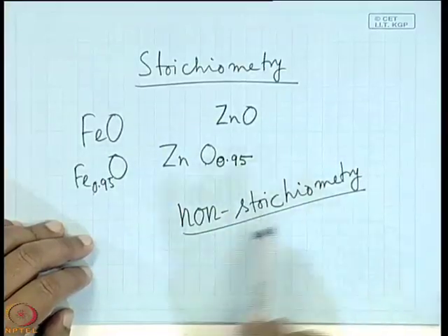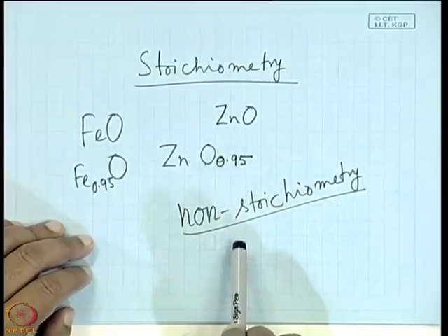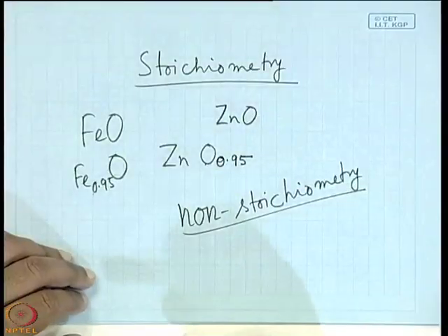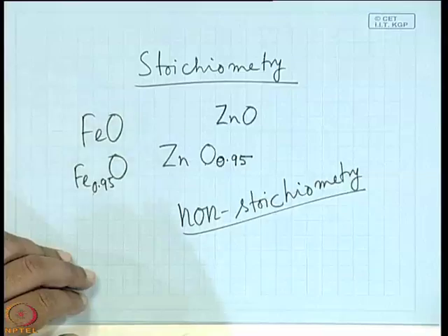That is the reason, because of this non-stoichiometry. In nature these materials are non-stoichiometric. There are oxygen vacancies, and in different materials, say zinc telluride, maybe there is zinc vacancy or tellurium vacancy. As you go on increasing the doping concentration, it will first compensate. Because of self compensation, the effect of doping will not be visible.